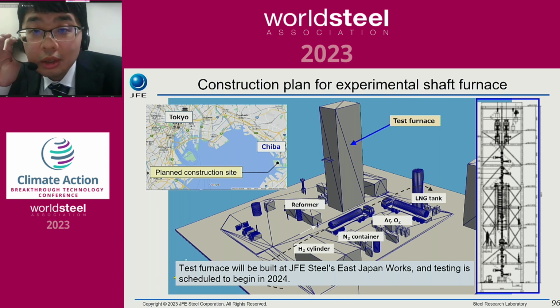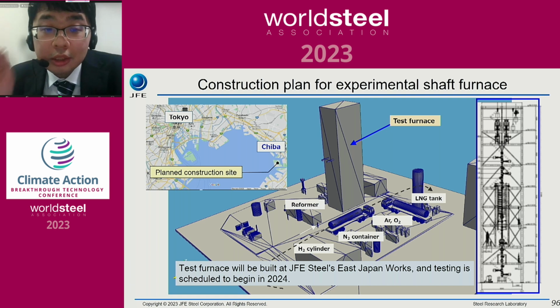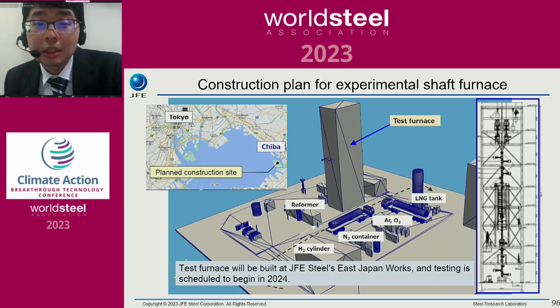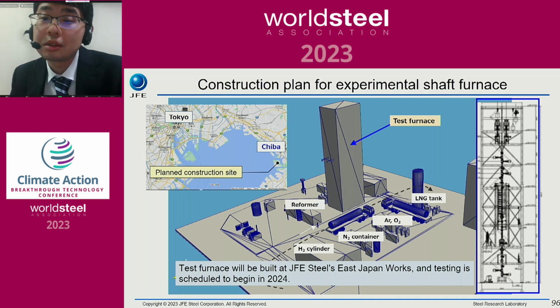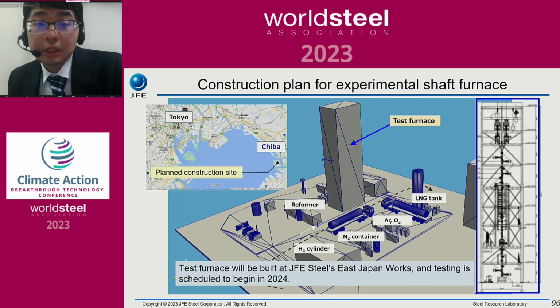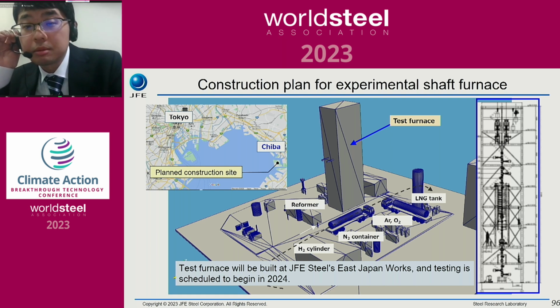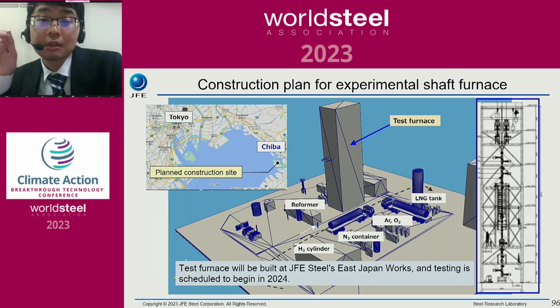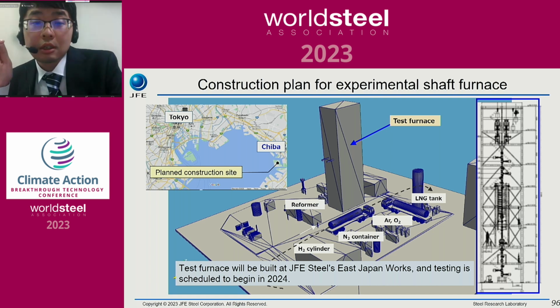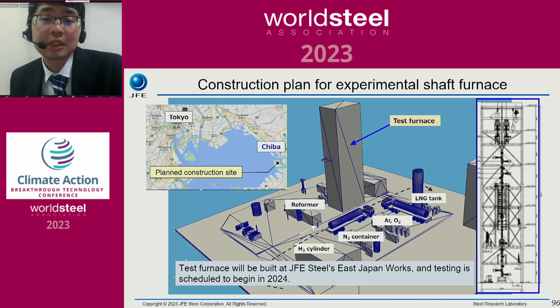The construction site is shown here near Tokyo, and DRI is produced at a standard rate of 0.5 ton per day. We can change the composition of reducing gas over a wider range, and the pressure within the furnace can also be varied. After the start of operation of this equipment, the influence of the reducing gas conditions on the productivity and the reduction degradation that may occur when using low-grade pellets will be investigated from 2024.